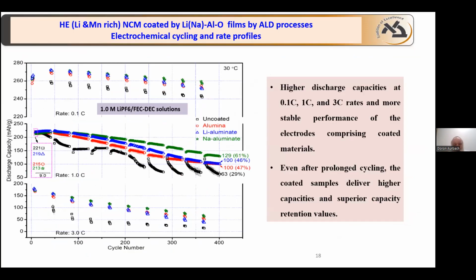And I show you two examples. One example is using ALD. We use aluminum oxide compound with lithium or sodium, and we form a buffer zone with a thickness of several nanometers, and we revolutionize the results. So what I show you here is cycling results of cells.